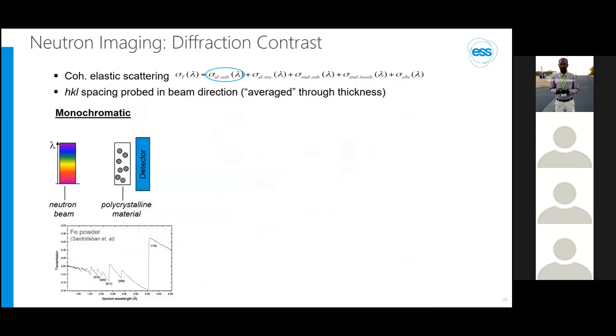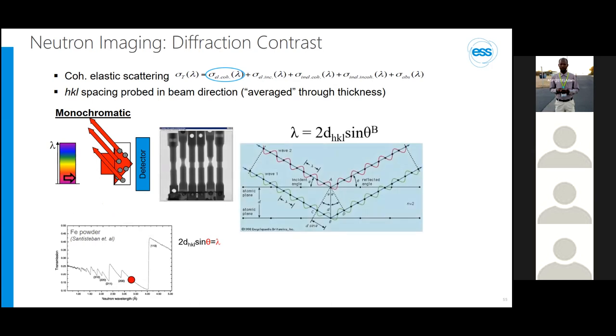The method itself is often also termed Bragg edge imaging, and in order to understand the examples, I will first briefly explain how it works. We record the transmitted neutron beam with a wavelength resolution, and what we are mainly interested in is the Bragg diffraction from crystal lattices, which is based on elastic coherent scattering, which is one of the contributions to the total cross section. Like I've shown you before, if you shoot monochromatic neutrons at a polycrystalline sample, some neutrons scatter according to Bragg's law at a certain angle, and this is what we usually detect in diffraction methods.